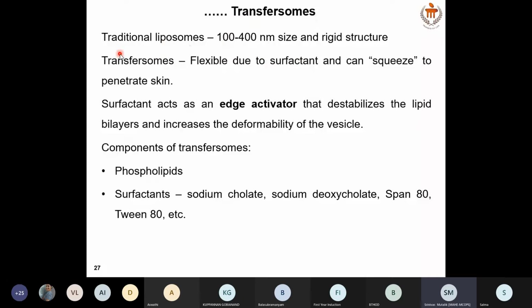And in transferosomes, usually we will not include the cholesterol or only with very low percentage, but we will add the surface active agent, for example, deoxycholate, or we also can use the non-ionic surface active agents to make the vesicles more flexible. Sodium deoxycholate is the classically used surface active agent in case of transferosomes. Surfactant acts as edge activator that destabilizes the lipid bilayers and increases the deformability of the vesicle.